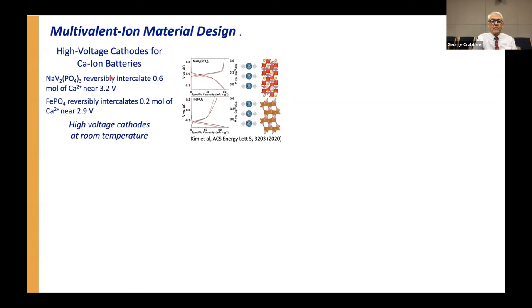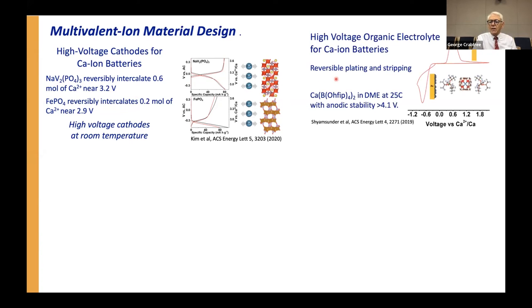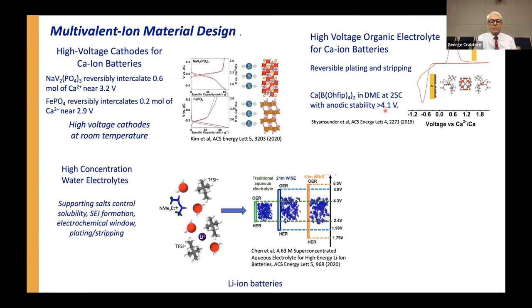But starting the discovery process again, here are two cathodes, iron phosphate, which we did use for lithium. That also works for calcium. But what works even better is this vanadium phosphate, which gets near 3 volts and stores a lot more calcium. There also is a lot of progress on the electrolyte, again, for calcium batteries. This is an organic one, works at room temperature with an anodic stability of 4 volts. So there are plenty of opportunities here to make the next generation multivalent battery.